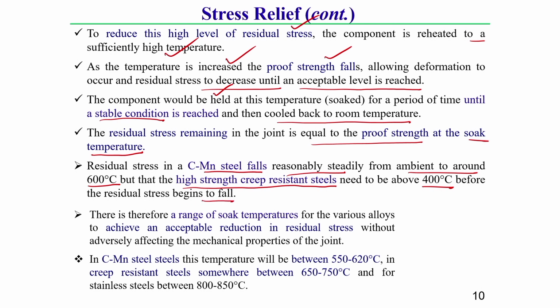That means, in case of carbon manganese steel, the residual stress starts to fall from ambient temperature to 600 degree centigrade, whereas for high strength creep resistance steel, the falling of residual stress needs an initial temperature of 400 degree centigrade. This you should keep in mind. So, there is a range of soaking temperatures for various types of alloy to achieve an acceptable reduction in residual stress. And another thing you should keep in mind, this temperature should not adversely affect the mechanical property of the joint.